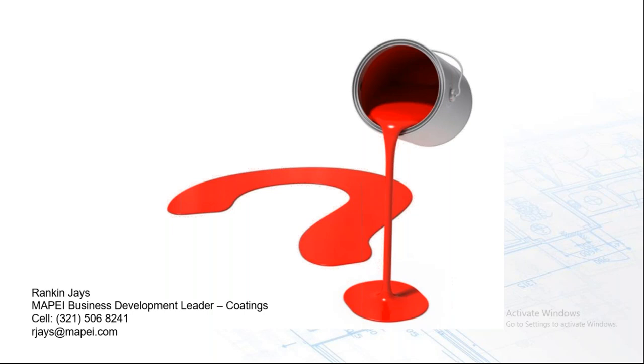When we're coating a structure, we start with, I'm assuming, a zero crack or a hairline crack, and the 1062-7 test, the European standard, does actually start from zero and elongates or expands that crack at a specific rate, and observes for any minor fracturing in the coating. The elongation, the other ASTM test that I referred to earlier, those also expand at a given head speed or a given rate, but usually the elongation is measured at failure, at complete failure, where the coating sample snaps, rather than identifying an early failure or an early pinhole in the crack bridging test.